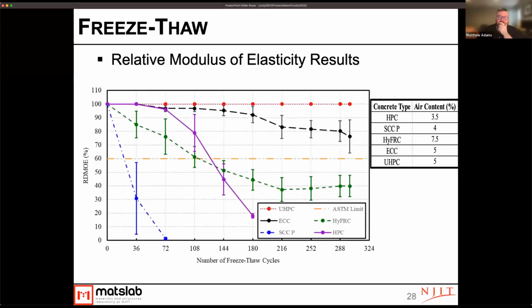For freeze-thaw, our two systems that were ordinary concrete, the SCCP and the HPC, both failed fairly early on. But again, those systems, we had a lot of trouble getting air entraining in. So this makes sense. The air entrainment was really quite low for those. The HyFRC also failed despite having 7.5% air content. And so that shows that HyFRC may not be the best choice in freeze-thaw applications.